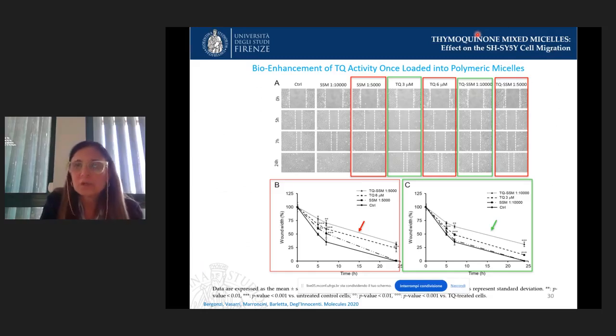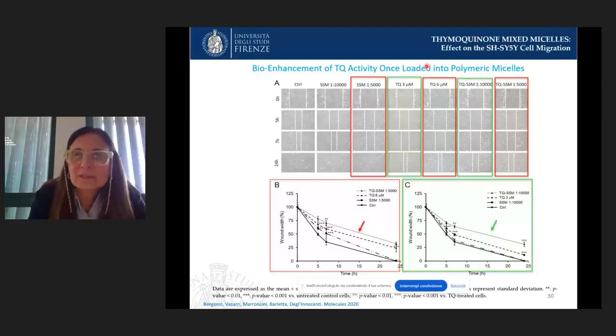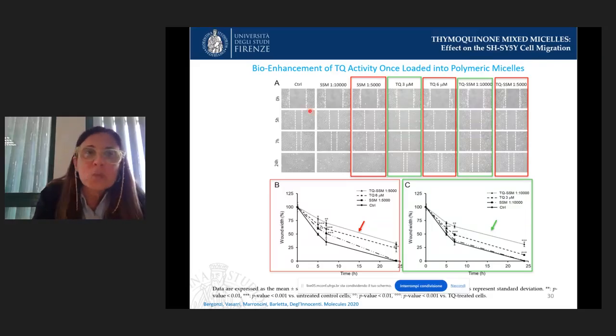From the literature, thymoquinone is an anti-proliferative compound that inhibits the development of tumors. In this case, we tested with the scratch test the influence of thymoquinone, and in particular of the formulations, on the cell migration of neuroblastoma cells. We can observe in figure A that here we have a layer of cells, and we produced a scratch inside the cells. We observed the reduction of the scratch during time. Here is the situation with the control.